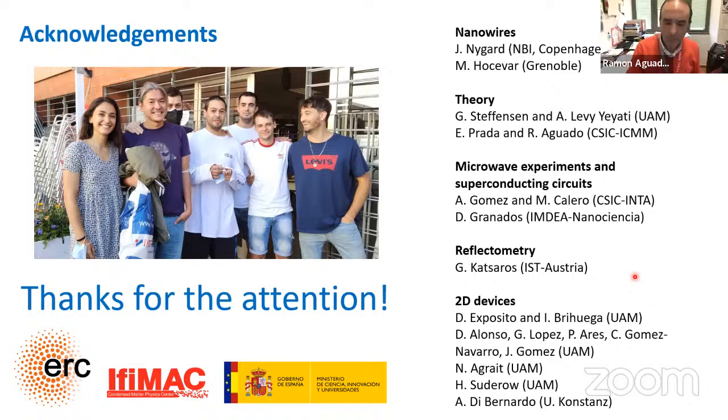Yes, go ahead. Hi, thanks, Eduardo, for a very nice talk, very interesting stuff. I was just wondering, in the analysis of heat conductivity and so on, it seems to me you consider electrons or quasi-particles, right? Do you consider phonons at all, or is it reasonable to ignore phonons when we have a superconductor? Yeah, so we estimated what would be the cooling power by electron-phonon coupling, and we estimated it to be about 2 orders of magnitude lower than quasi-particle. So it's true, as you say, the modeling that we take into account only considers quasi-particles as a heat dissipation mechanism. All right, okay, thank you.